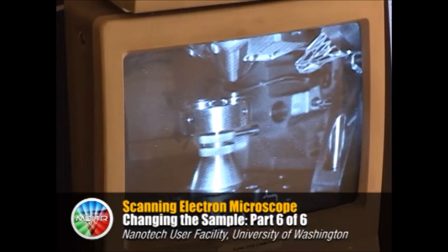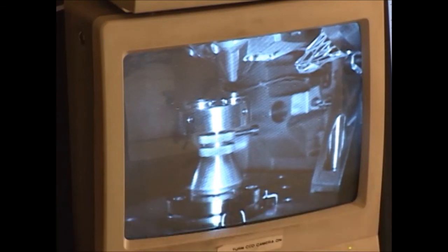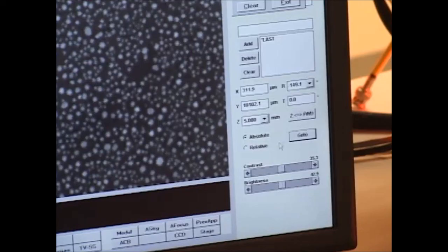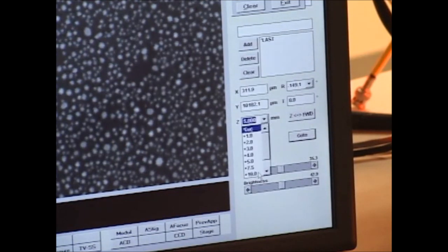Not all of our samples are exactly the same height, but for safety purposes we want to make sure they're within a couple millimeters of the same height of one another. That way when I move over to the next sample holder, I'm not in any real danger of hitting the detector. To be sure that I'm not too close to the detector, before I move over, I'm actually going to drop the stage back down to 10 millimeters.